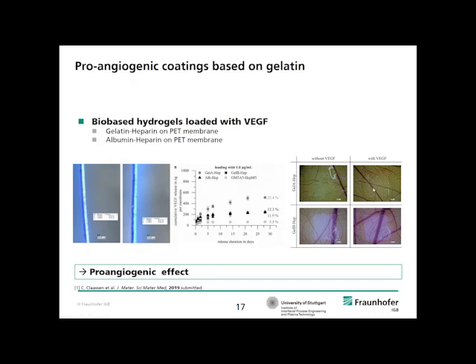And if we test the coatings in a CAM assay, the assay in a chick egg, you can see that without the growth factor, we have less development of vascularization within the egg than if we have here the coated membrane with this growth factor. Again, here for another coating material, the amount of small capillaries increases if we incubate the growth factor loaded coating on the egg yolk.